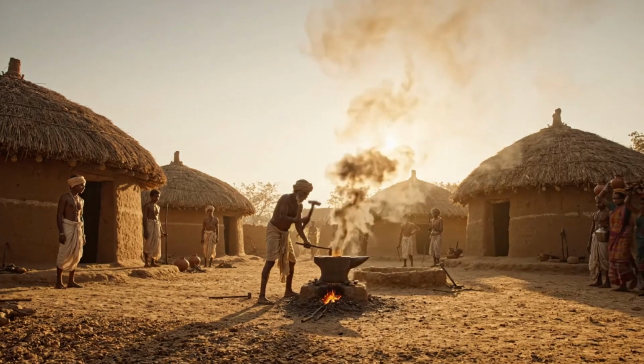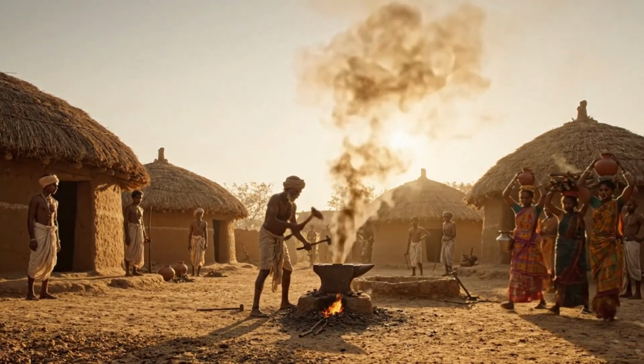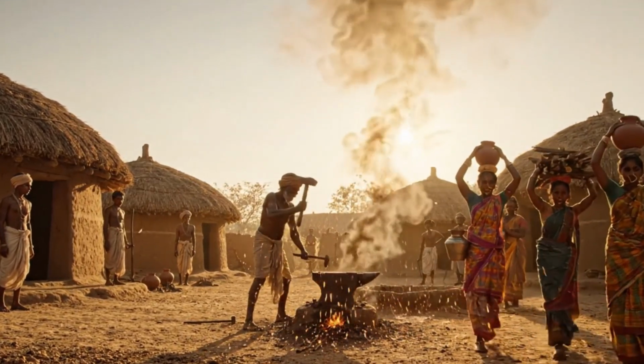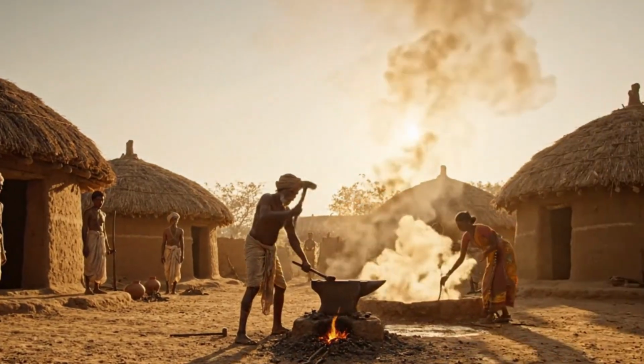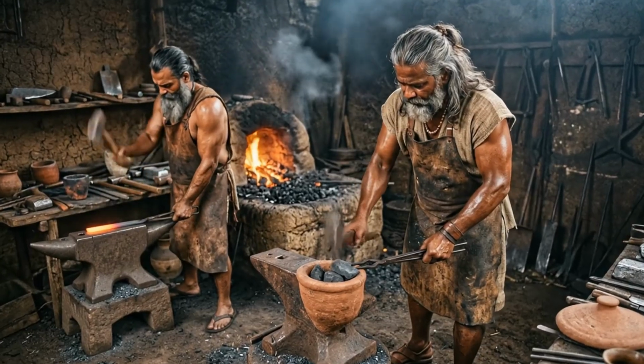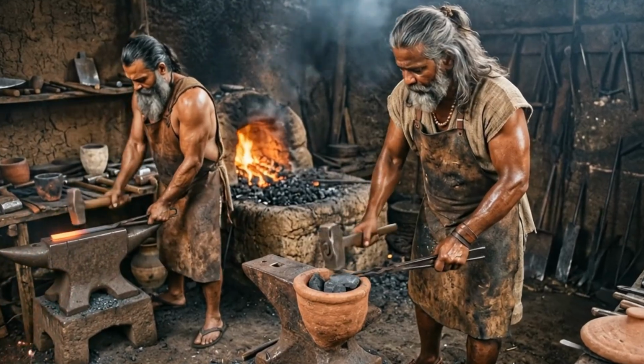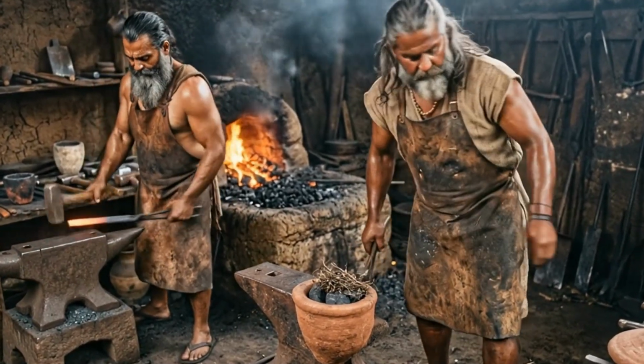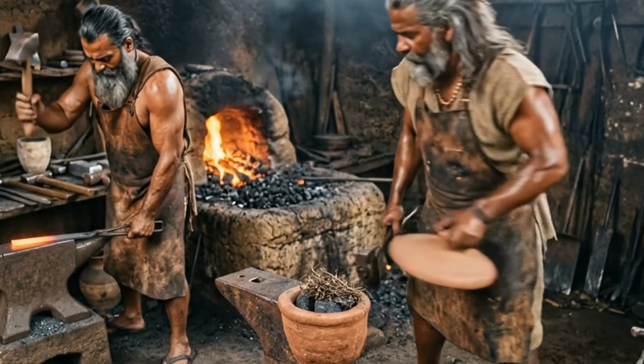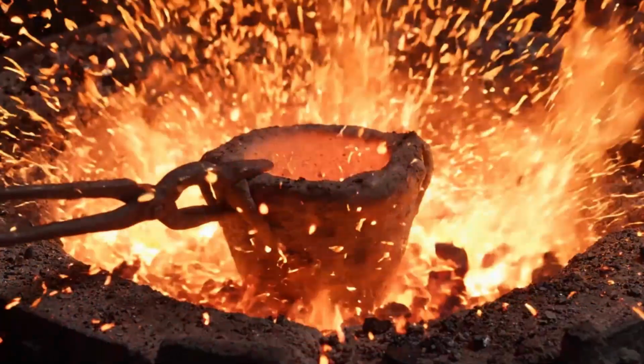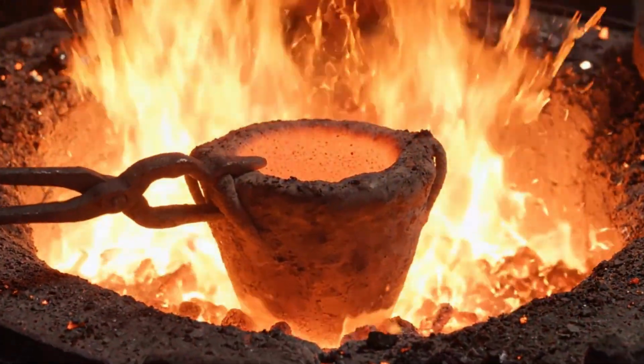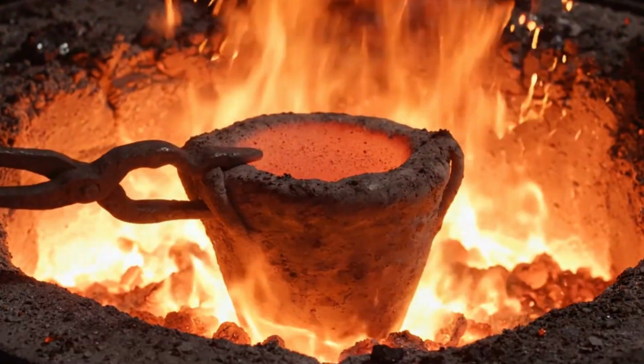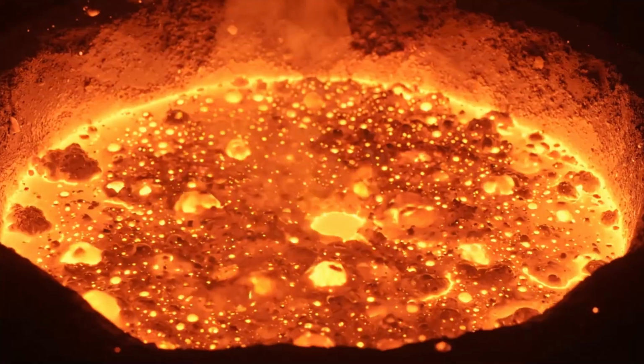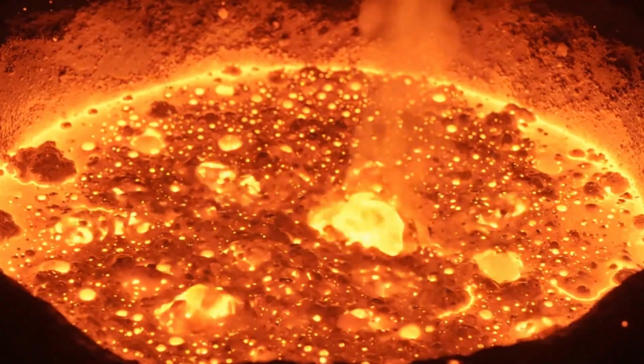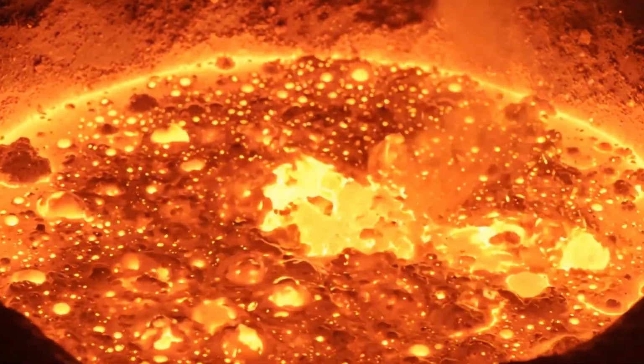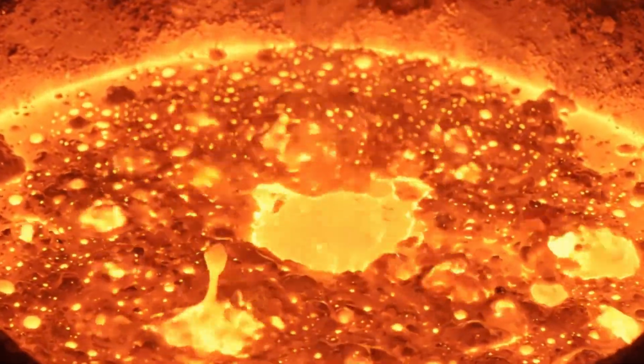The story of this confusion begins with the original Damascus steel, known historically as Wootz. This remarkable material did not achieve its distinctive patterns by welding together different pieces of iron. Instead, its creation was rooted in an ancient Indian technique, with the finished product often traded and forged in Damascus, Syria. The process involved placing iron and organic materials like wood or leaves into a sealed clay crucible. This crucible was then heated to extremely high temperatures, causing the contents to melt and fuse.